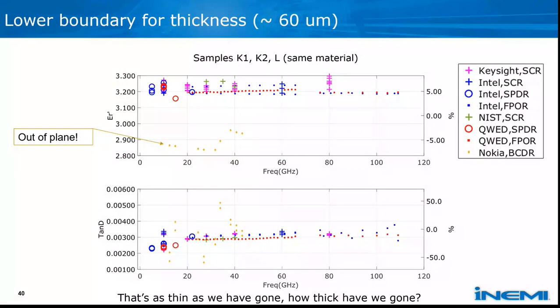Something I think is exciting is that if we add in the BCDR measurements, which measure the out-of-plane permittivity, uniquely compared to the other three measurements we considered, you can see this out-of-plane permittivity is more or less 10% lower than our in-plane measurements. But otherwise they're all grouped very nicely, and our loss tangents are all grouped pretty nicely too.